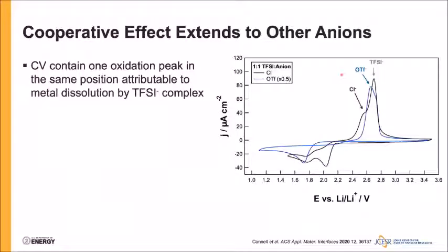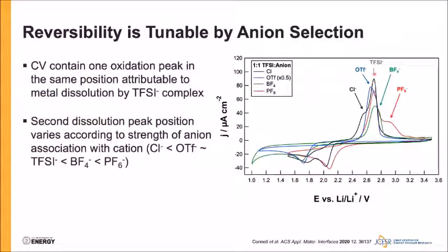So we return to the predictions of DFT and start to compare anions of differing association strength. What I've already shown, the TFSI chloride and TFSI triflate case, we see the additional oxidation event at lower overpotential relative to the TFSI only. If we move to more weakly associating anions, though, very interestingly, we see the location of this additional oxidation event shift to higher overpotential, in direct analogy to what's predicted by the DFT. And in the case of PF6, we also see the onset of reduction start to creep more positive of that with the TFSI only system, which is again consistent with this idea, because with a more weakly coordinating PF6, it should be easier to desolvate the zinc cation relative to TFSI.